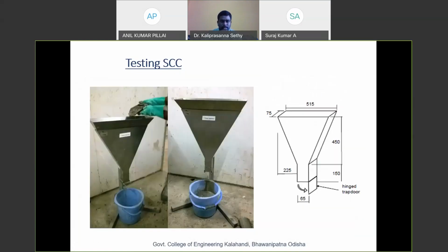And here is the viscosity test, which is conducted using the V-funnel apparatus. As you can see from the diagram pictures, we are pouring the concrete inside this V-funnel, and here is a shorter hinged trap door. Once we remove the trap door, we have to take the reading of the flow time, meaning how much time it takes to empty from this V-funnel into this bucket. There is a range given in the EFNARC guideline, so from that guideline we can certify this concrete as self-compacting concrete.